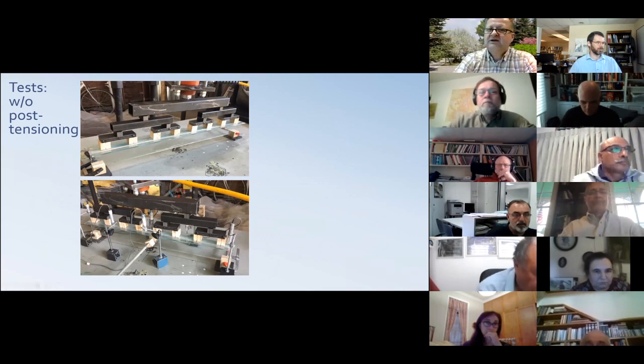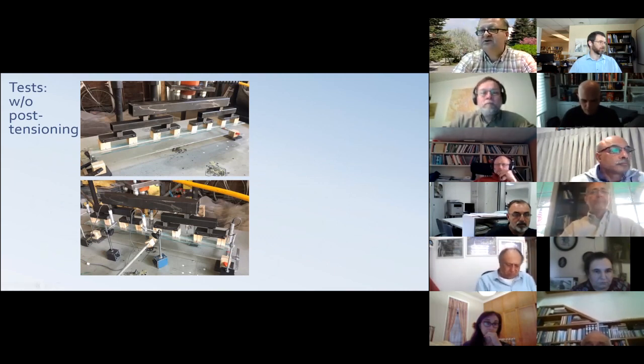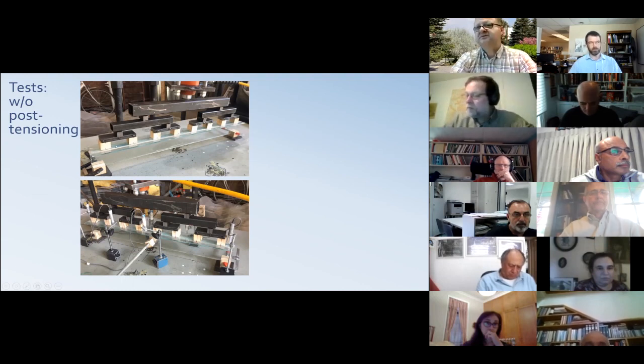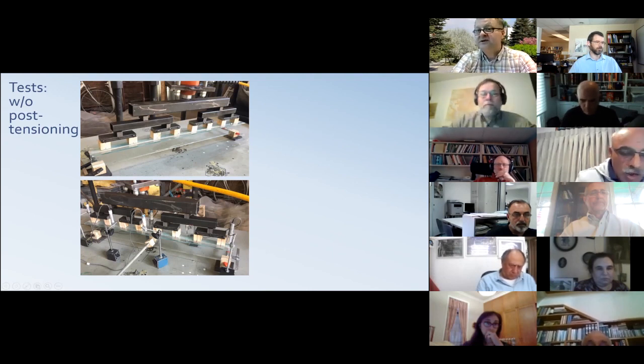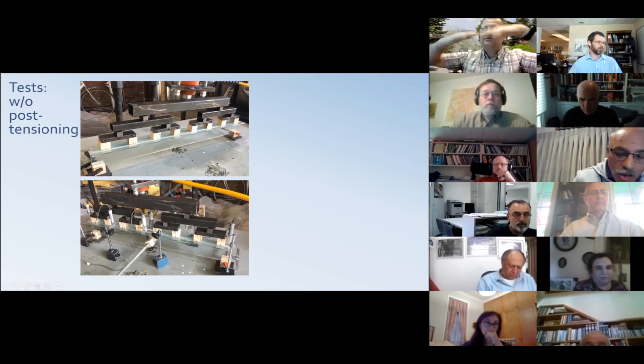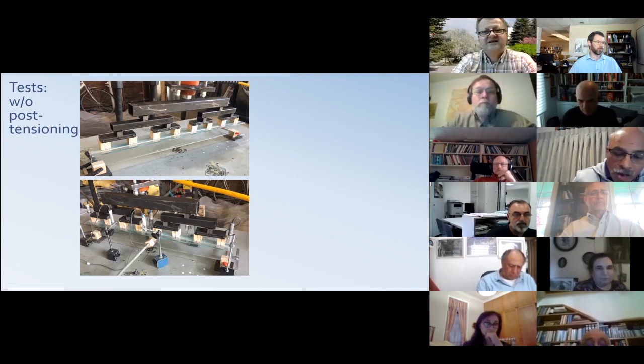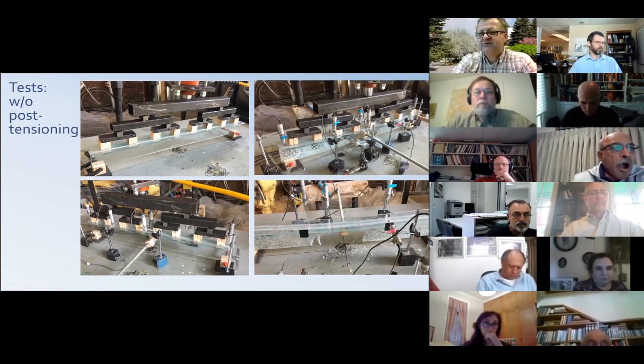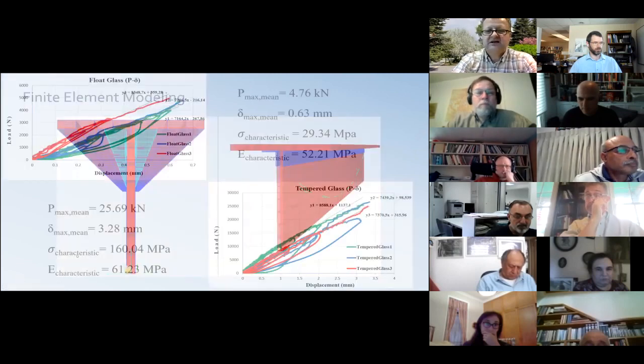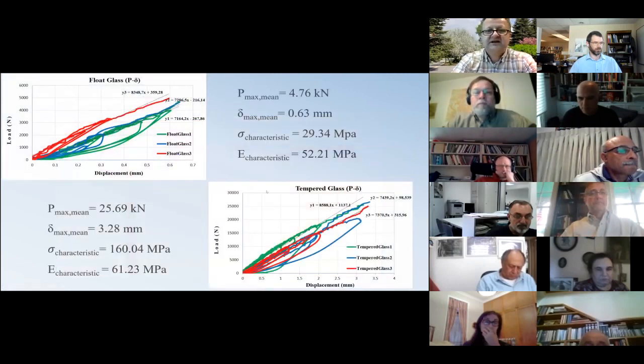When you apply a load here, it is statically divided into two. So you don't have to apply 8 different pistons, but instead have a simply supported beam, and then each one simply supported, and then each one simply supported. So whatever force we apply, we divided it into 8 equal pieces, which is independent of the deflection. So that was a nice setup. And the results that we have obtained with the regular glass, it breaks, and with tempered glass, it breaks. And then we applied the post-tensioning, and we did all the additional tests.